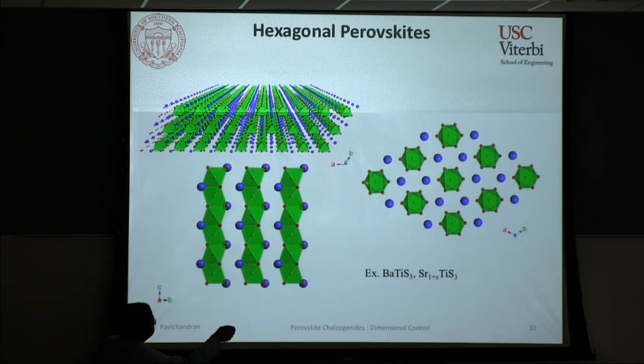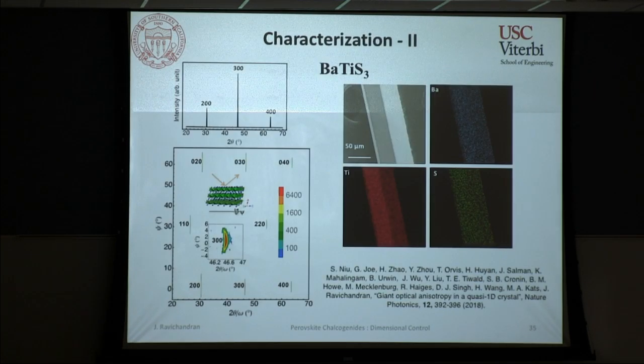So this is your A-axis, and your B-axis is at 60 degrees away. So basically, by taking the crystal, aligning it along the A-axis, and then rotating it by 60 degrees, you should access the B-axis. So that's what we did here, where you first start with the A-axis, and then you rotate it by 60 degrees, and now you achieve the B-axis. So that tells you that you have your crystal like this, and your B-axis somewhere inside your system. That means the axis perpendicular to the A-axis is your C-axis.